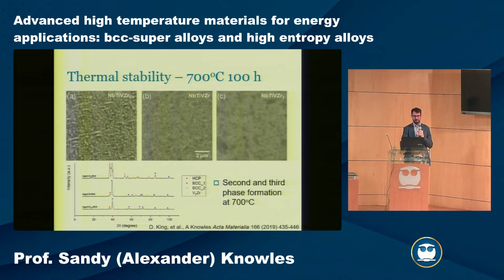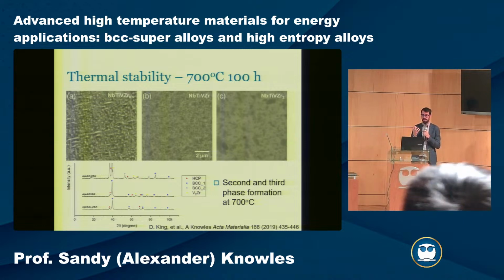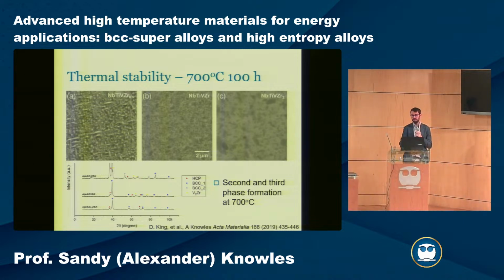With a bit of painful work, we can do TEM as well as SEM, EDX, and X-ray diffraction, and work out which phases they are. In this case, we do get quite similar phases to what is predicted by CALPHAD, but at different temperatures. So CALPHAD gets some of the way there, but it's not enough to truly design an alloy. It gives us an indication, but it doesn't have sufficient accuracy yet.